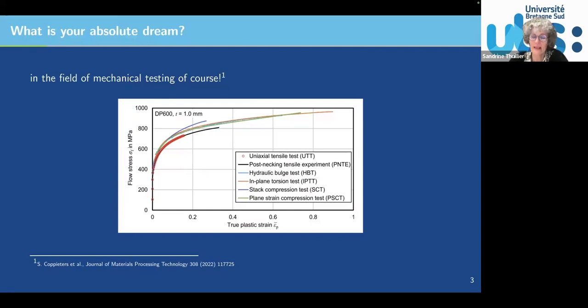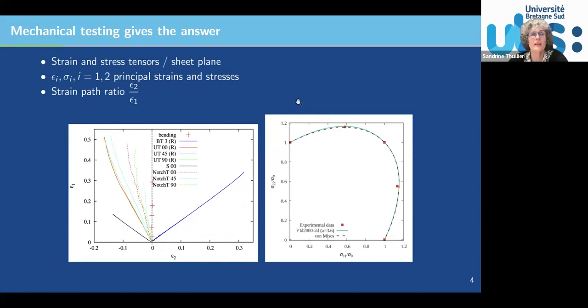And as you know, mechanical testing will give you the answer. And when you consider a sheet metal, you mainly define the deformation mode, or the stress state, in the sheet plane. And here you've got the minor strain, and here on the y-axis, the major strain, and one straight line is one mechanical test. So you've got biaxial testing, simple shear, tension here, and tension with necking, so it's not really a linear strain path. And for each curve, you need a mechanical test.